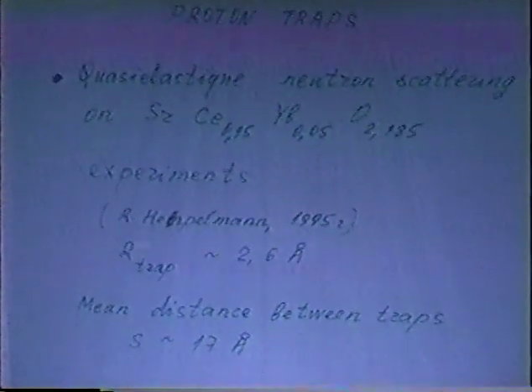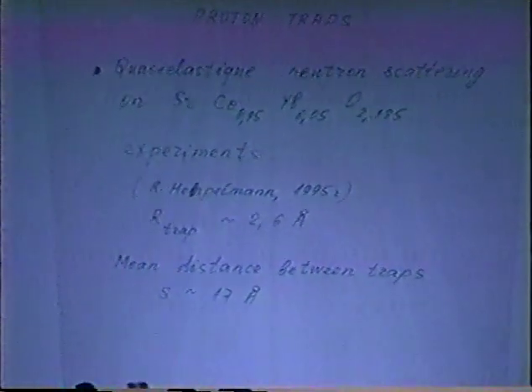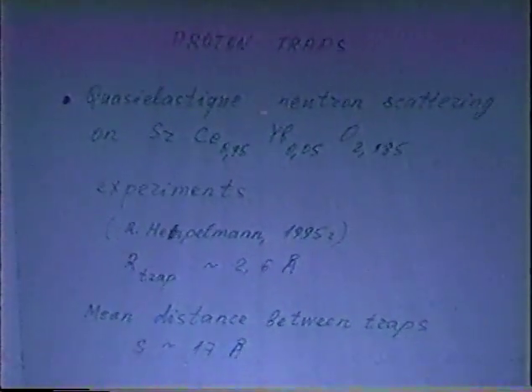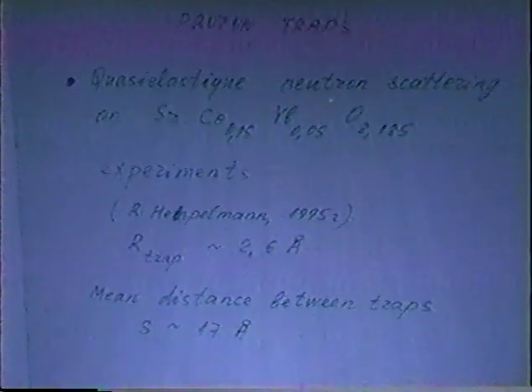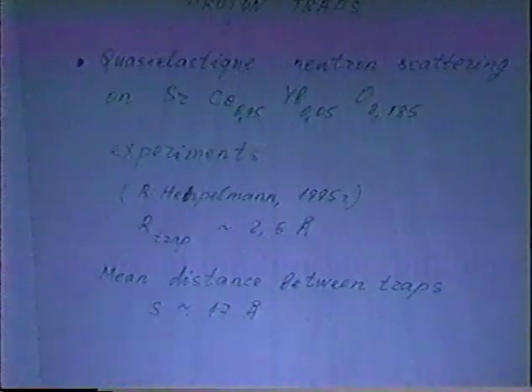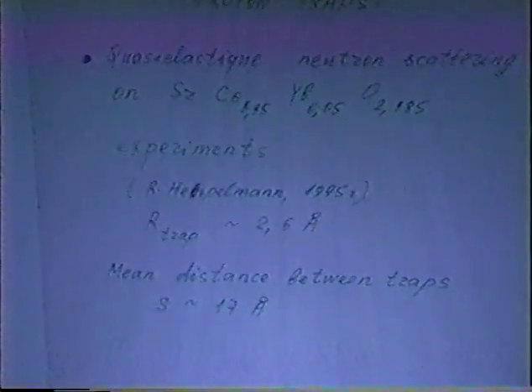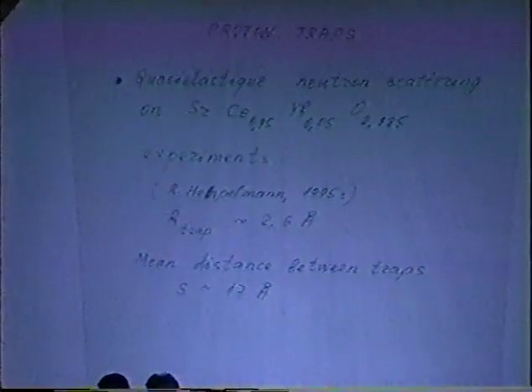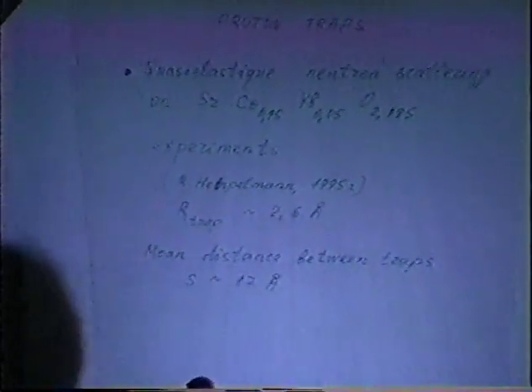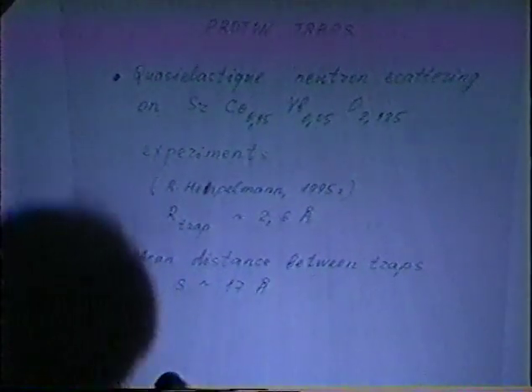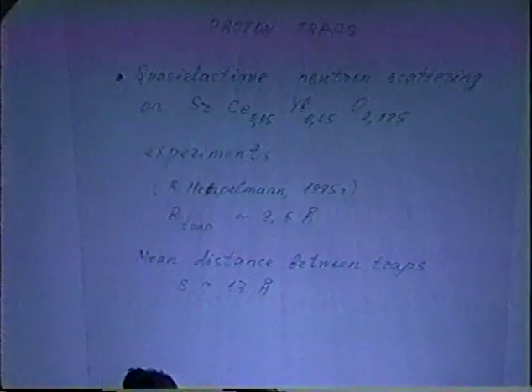The experiments of 1995 by Hempelmann, as regards quasi-elastic neutron scattering upon strontium cerate, showed that proton traps really exist within the samples. The traps with a radius of 2.6 angstrom can immobilize the protons.